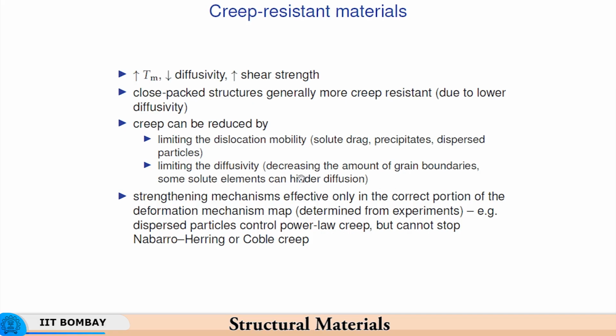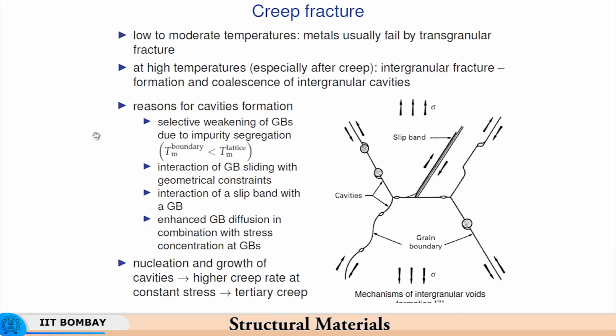So, if you limit the diffusivity by removing the grain boundaries or minimizing the grain boundary area, then one can minimize the diffusion paths. The least you can do is have a single grain. You have one grain, and whatever grain boundary area it has is the minimum you can have. You can't reduce the grain boundary area below that. Plus, you have some solute elements which can also hinder diffusion. So, these are the various steps which can be taken to make the material creep resistant.